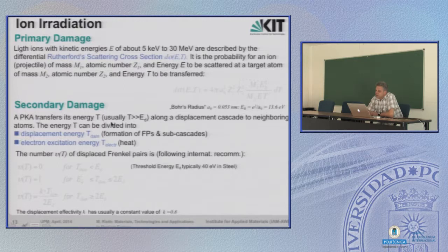Here, the energy T is best divided into two parts. One is the energy T which really causes damage, which displaces other atoms. That's the displacement energy T_dam. Or the energy which only produces heat by light emission and so on. That's the electron excitation energy T_electron.